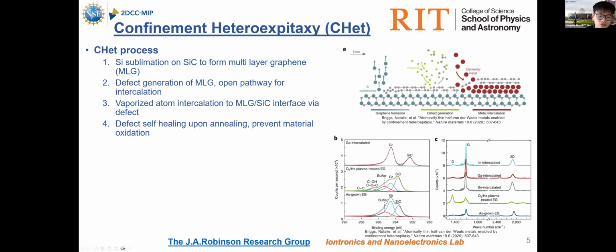And also on the Raman, at the bottom is the as-grown graphene. It doesn't really have the full fingerprint of graphene as we know it, the D, G, and 2D peaks. And as you treat it with the O2 plasma, you see a significant increase in the D peak, which implies an increase in the defect density, which is the pathway for intercalation. And as you intercalate, this D peak decreases and the G peak increases, which means that the defects will actually self-heal while the atoms intercalate, decoupling the bonding between the buffer layer and the silicon carbide substrate, improving the graphene quality. Basically, that's what the increase in the G peak means.